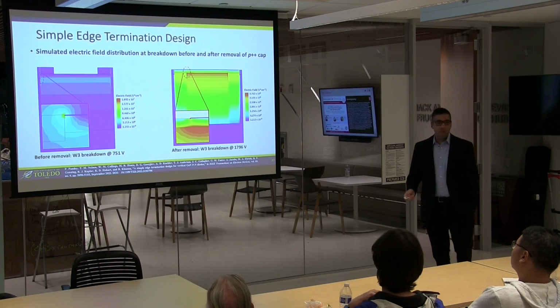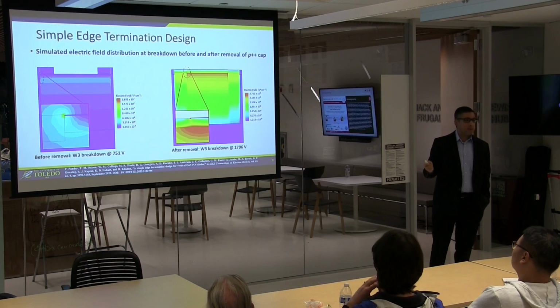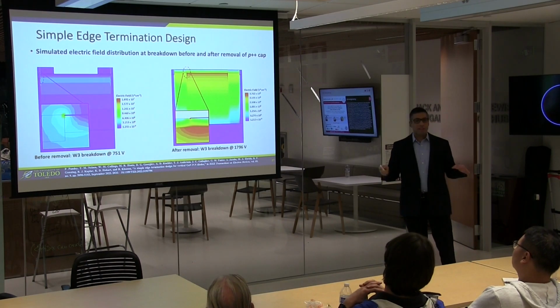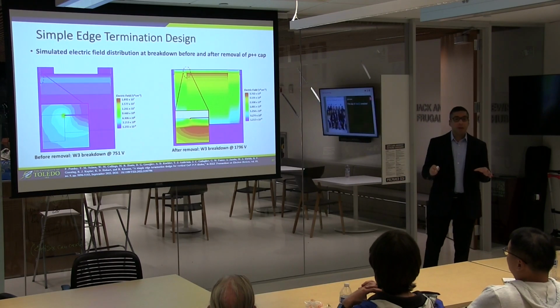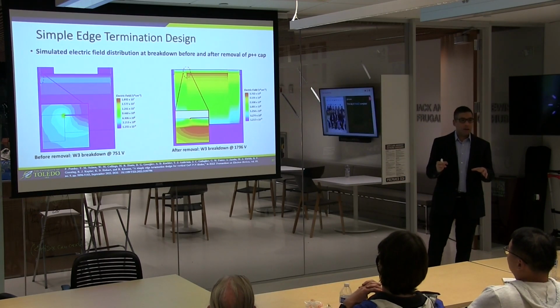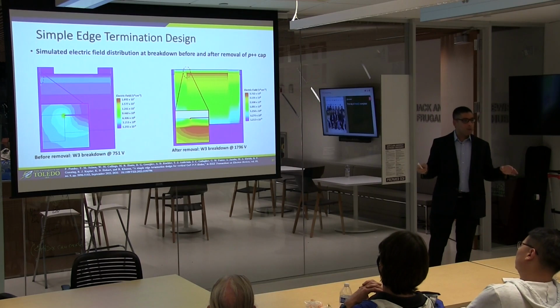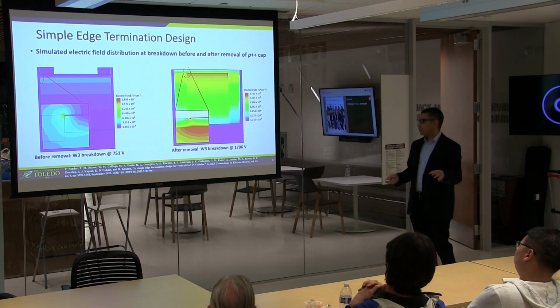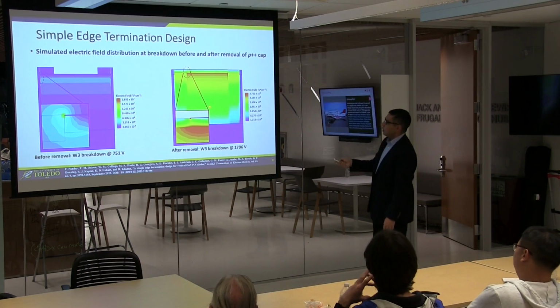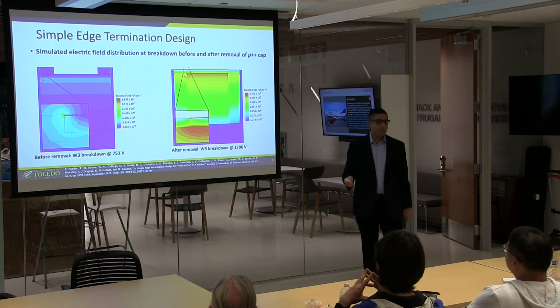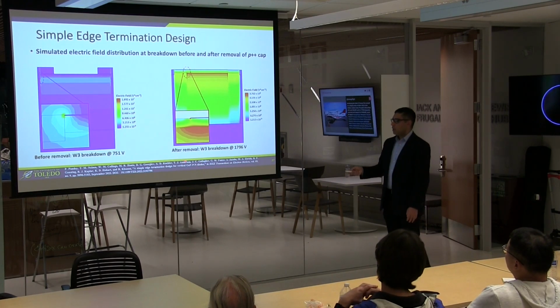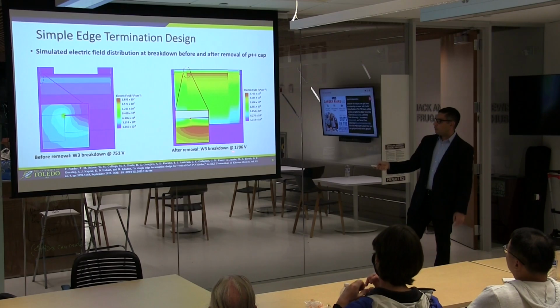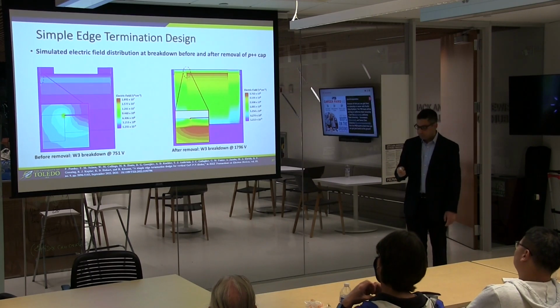So what we did was we went into simulation and we removed that P+ capping layer everywhere except underneath the anode. So we kept it underneath the anode so we can maintain that contact resistance, but we removed it from underneath the silicon nitride passivation layers. And then what you see here is you get much more uniform electric field distribution. You get an improved breakdown performance from 750 volts to 1800 volts.